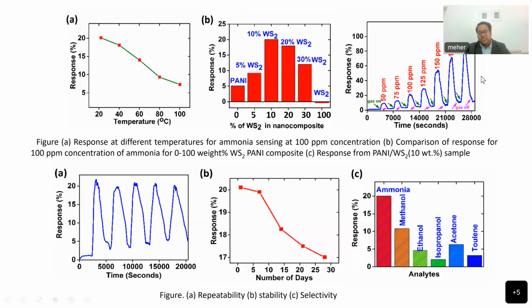And this is also a temperature profile of the sensor. So if we increase the temperature, the response is decreasing with the temperature. So it's working best at room temperature. And this is the time. So with time, how it is degrading, and it is not degrading that greatly. In around 1 month, around 3% of response was decreased. So this is not very appreciable.